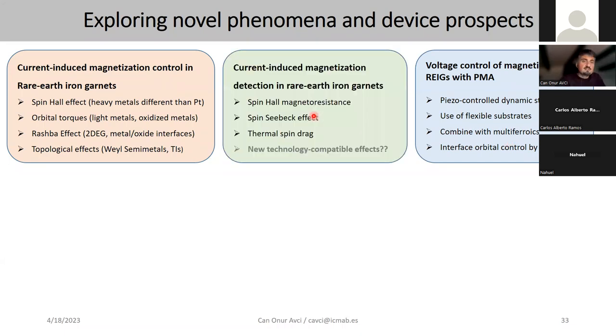And finally, the last challenge is that I've shown you some ways to detect magnetization in local and non-local devices, but these signals are either very small so far or not very compatible with the industry, because you cannot make Hall bar measurements if you want to build a memory element. So you need to adapt your detection technique. Spin Hall magnetoresistance is good, but it's not enough. The geometry is not enough. The spin Seebeck effect can only detect an in-plane component and not the out-of-plane component. Thermal spin drag is still a very small signal. So we need technology-compatible new effects, and we are working on it.